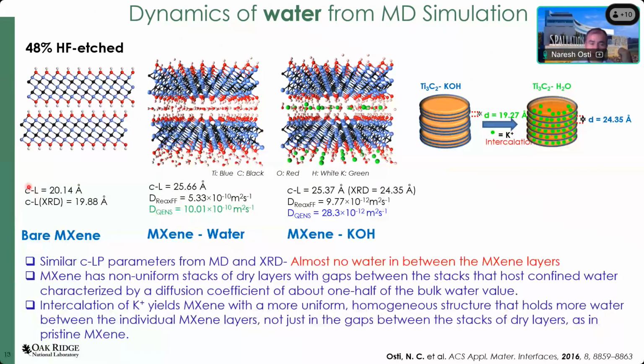Now, if you look at the C lattice parameter that you obtained for the bare MXene, it matches nicely with the C lattice parameter that you obtained from the XRD. It means that in pristine MXene there is nothing in between the layers. That means the diffusivity of the water that you measure is not coming from the water that resides in between the layers.